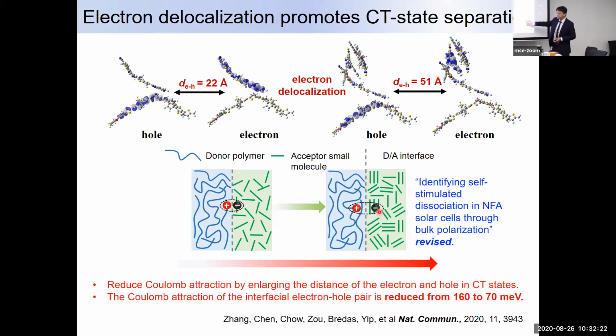And of course, we have another paper trying to further understand another mechanism, which is the self-stimulated dissociation, right, of the exciton. What we find out is when we try to increase the excitation density for this Y6 molecule, it gets self-polarized, bulk polarization. If it is polarized, the dielectric constant increases, reduces exciton binding energy, and it's easy to separate. So there are several different possible mechanisms to show you, right, why this is an amazing material.